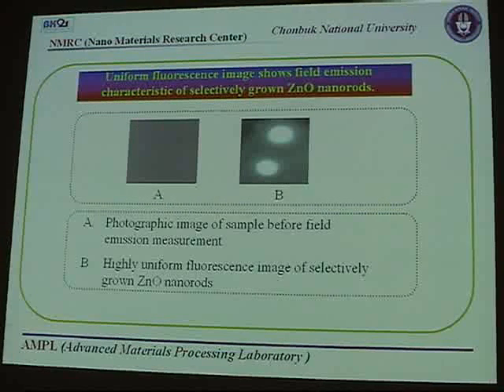This is a uniform fluorescence image during the field emission. When we apply the current, we can see this is the substrate area we captured before the device measurement of device performance, and after, during the measurement, we find the uniform fluorescence image in these spots, which shows that these zinc oxide nanorods can be a very good candidate for field emission devices.